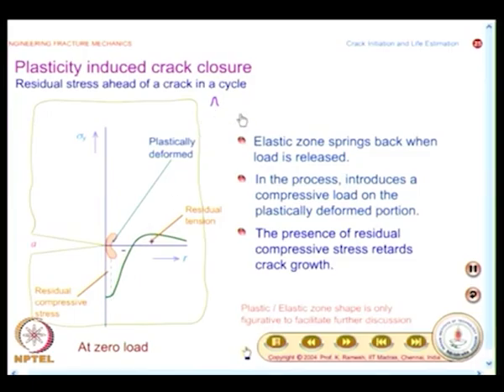At the end of one cycle, invariably you will have a residual stress pattern which is compressive near the crack tip and tension ahead. And let us see what are the steps. The elastic zone springs back when load is released. In the process, it introduces a compressive load on the plastically deformed portion.